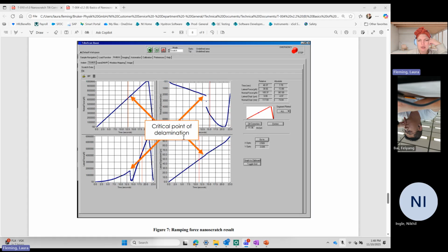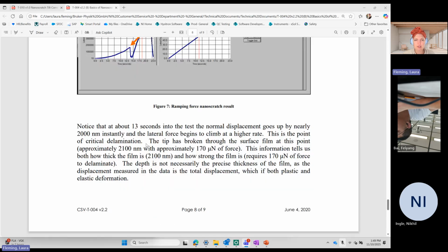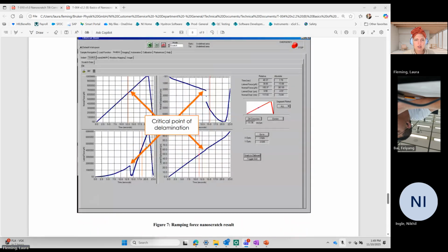But when you're looking at what the scratch is actually doing, critical point of delamination is pretty common. So in this one, we have this ramping normal force, and this is the scratch. This is a different transducer, but it shows the same behavior. And you can see here that at this point, all of a sudden your lateral force begins to climb at a higher rate as your normal displacement increases. So you've broken through the sample in such a way that it usually causes some sort of bump in the lateral displacement and your lateral force as that tip punches through the sample surface. So that's some analysis that you could also do. What force does that critical point happen at is what people are typically looking for.